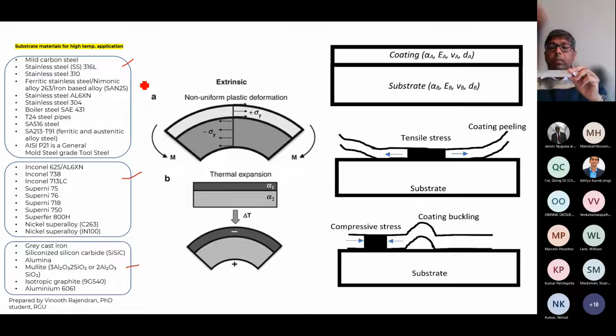Based on the strain being built up during coating, things will deform. Either it will go this way, where you have a huge tensile stress, or you can go this way, where you've got a huge compressive stress. So a high extreme of those is not desirable. You would like to have a residual strain built in during manufacturing, which is sustainable under external mechanical load. So this mechanics we have to be aware of, how the coating will form.